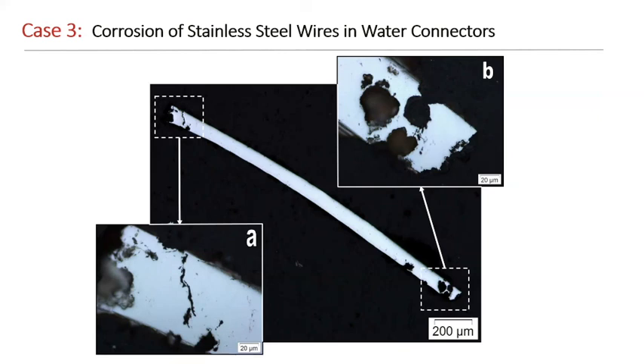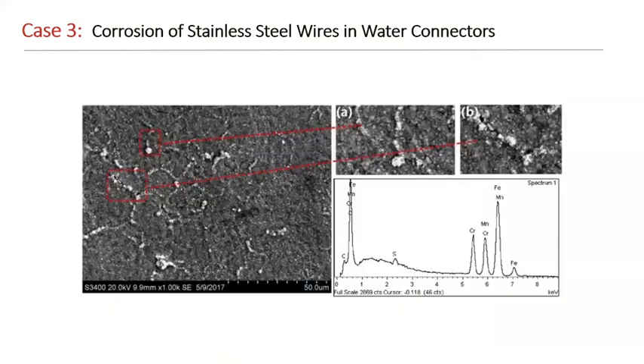However, there are sometimes steps in the manufacturing process that are not done correctly, which makes these wires more susceptible to this type of failure, where some identical wires would not fail, or what looked like an identical wire would not fail. A wire that hasn't been manufactured properly would show, for instance, like I'm showing in this case, some areas where the composition is different, or some improper heat treatment, which, even though you have the right composition, you have the wrong microstructure, and that makes it easier to fail as a result of one of these corrosion types.